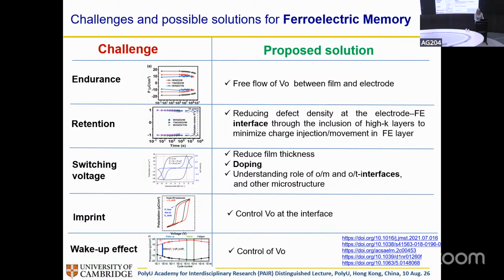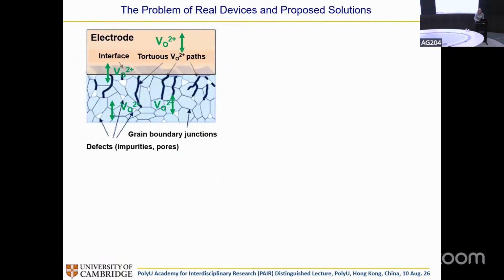That's what we need to do, is to think about all these problems and try to solve them. So if we think about what a thin film looks like in a cross-section, on the left here, we see that we have a film. Ideally, you'd want a single crystal, but oxides have very high melting points, and it's very hard to make a single crystal in a practical way. If you think about a CMOS foundry, you want to do things at lower temperatures, you want to save energy, and so the way to do that is to make a polycrystalline material at lower temperatures, or even an amorphous one.